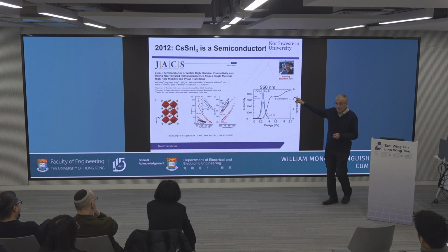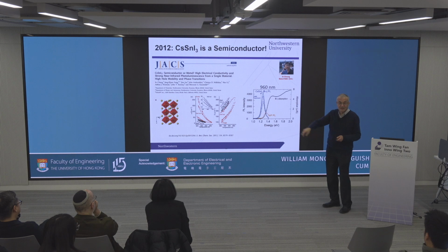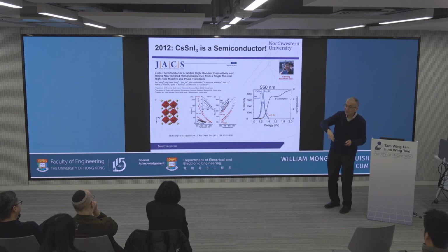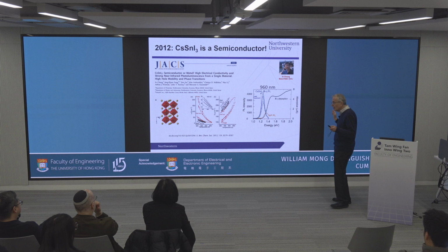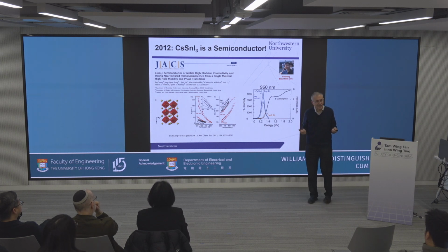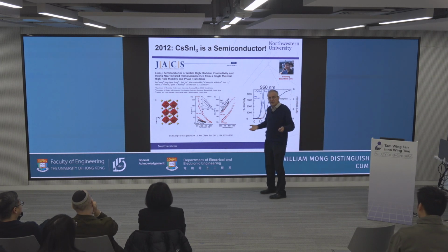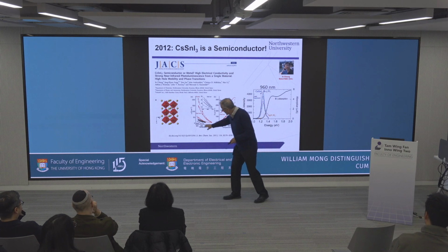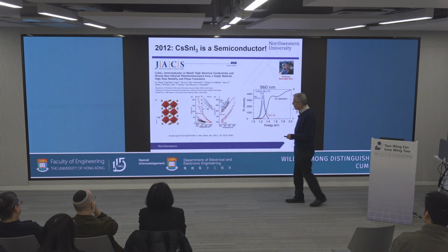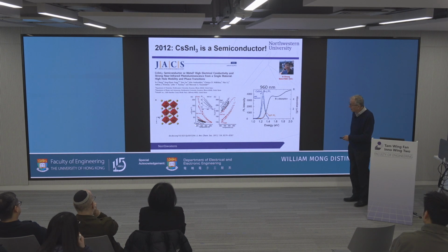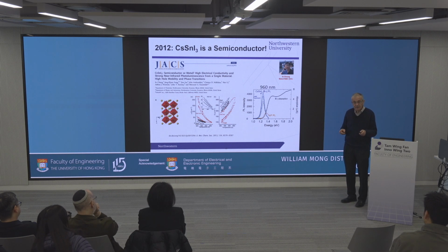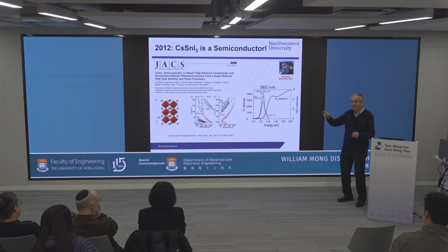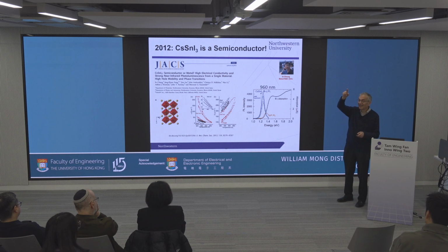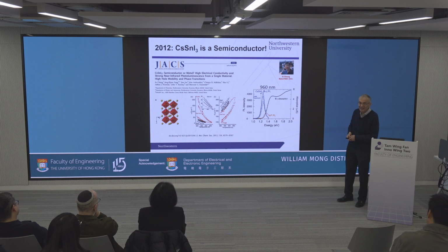But between 2008 and this paper, it wasn't always intense. We had problems. It was not reproducible. Sometimes it was weak. Sometimes it was strong. We were very confused. Okay, then how do I explain the metallic behavior? Well, let's measure the conductivity. This is conductivity versus temperature. The pure sample, the high quality fresh sample, is very low conductivity. But if you measure this in air and you heat and cool, and heat and cool, the conductivity goes up. And now this is the undeniable curve that is metallic.